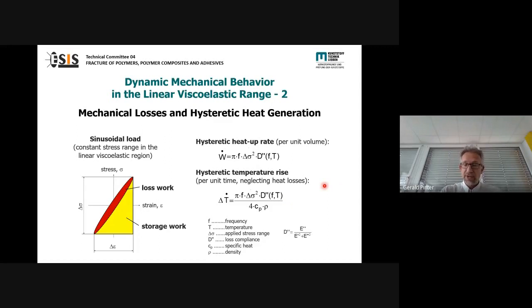So this is a very important aspect in dealing with fatigue. If you're doing fatigue tests, please always check the temperature development at the specimen directly. It can be done quite easily with infrared sensors, for example, so that you get a direct feedback if there is a temperature increase at the specimen or in the component.